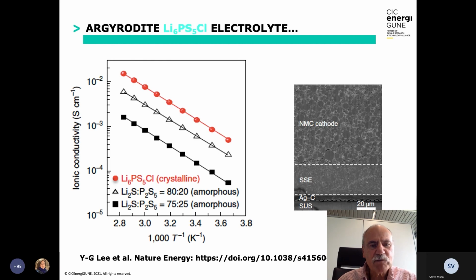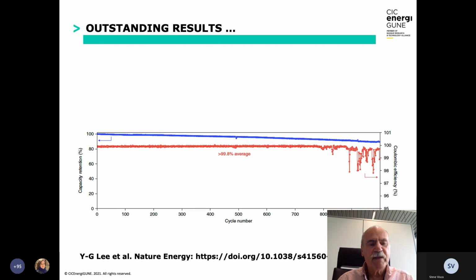With the argyrodite, you have got a different situation. The compound is highly conductive, as you can see on the red curve, and you can build a battery with an NMC cathode, high voltage cathode, a solid electrolyte which is argyrodite, and instead of lithium electrode, you have a silver carbon composite, which allows to deposit a silver lithium alloy close to the voltage of lithium metal. And this works extremely well. As you can see, a battery can cycle for 1,000 cycles with excellent Coulombic efficiency. And this is considered as a breakthrough, probably the best that can be made in solid-state batteries for room temperature operation.